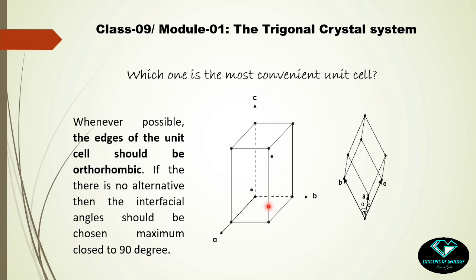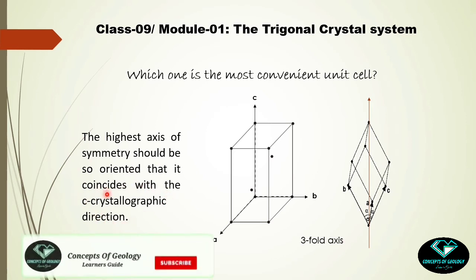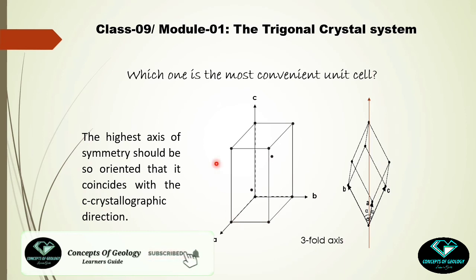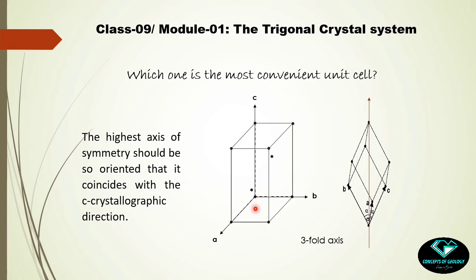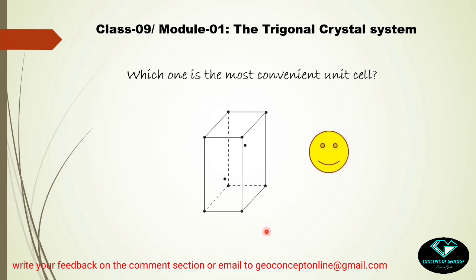Placing the two unit cells side by side: in the non-primitive rhombic prism, axes a, b, and c are orthogonal — mutually perpendicular. In the primitive rhombohedron, the three crystallographic axes a, b, and c are not orthogonal at all, since the rhombohedron is an inclined cube where no angle remains 90 degrees. Furthermore, there is a convention that the highest symmetry axis should coincide with the c crystallographic direction. In the non-primitive rhombic prism, c coincides with the threefold rotational axis — the highest symmetry present. In the rhombohedron, c does not align with the threefold axis. Therefore, the most convenient unit cell for the trigonal system is the non-primitive rhombic prism, which also shows pseudo-hexagonal symmetry.